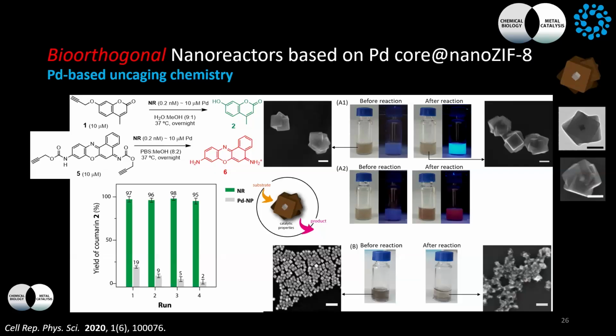Okay? There's a lot of controversy with palladium catalysts and what happens with them, particularly when they are nanoparticles. So our idea was to use the method that I told you to grow the MOF on top of the palladium cube to protect the nanoparticle and have like a nice sponge where the starting material can go in or has affinity to go in, get in contact with the surface of the palladium, do the catalysis of palladium, and go outside. And do this inside the living cell. Okay? So this is what we did here.